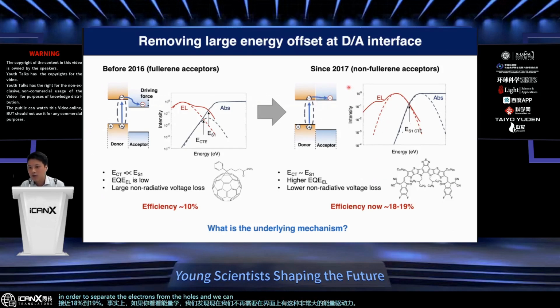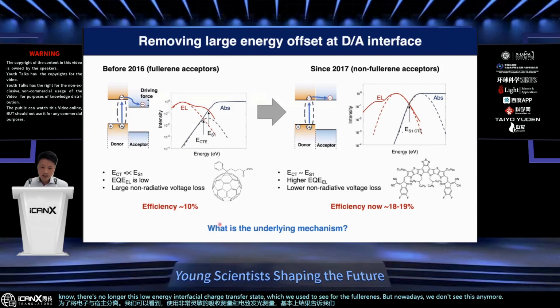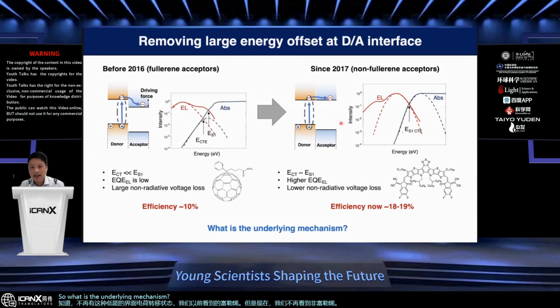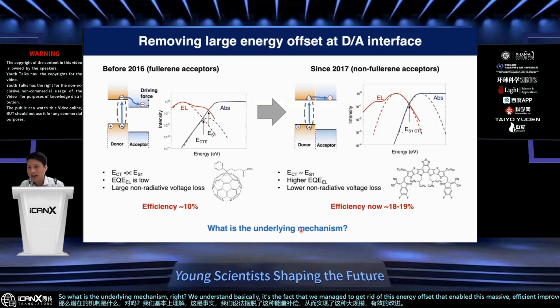And we can see that using very sensitive absorption measurements and electroluminescence measurements. Basically, the result tells us that there's no longer this low energy interfacial charge transfer state, which we used to see for the fullerenes, but nowadays we don't see this anymore for the non-fullerenes. So what is the underlying mechanism? We understand it's the fact that we managed to get rid of this energy offset that enabled this massive efficiency improvement. But how come? We're still relying on carbon-based materials. How come nowadays we no longer need this large energy driving force?